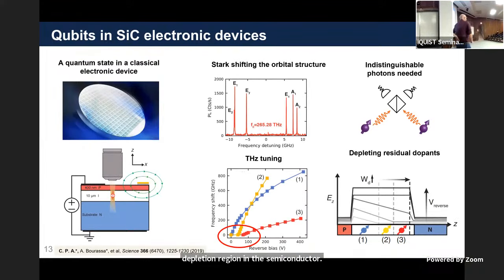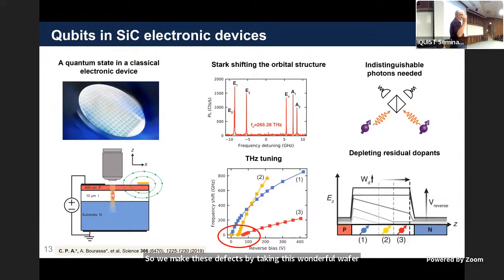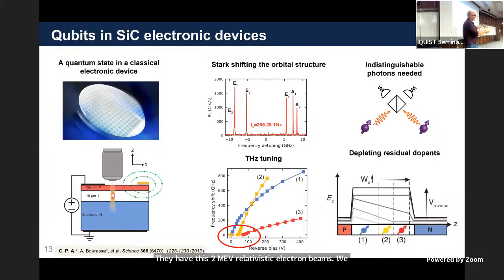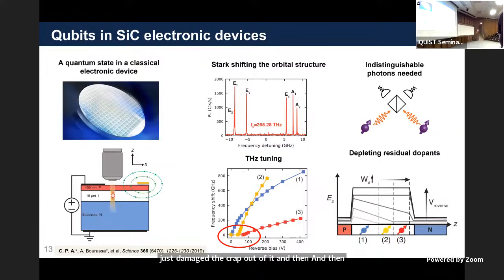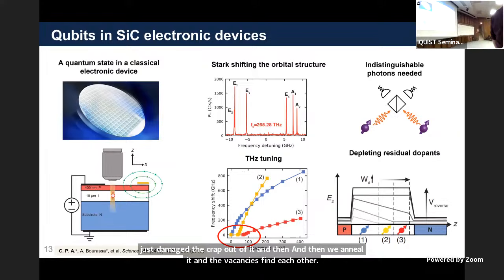So we make these defects by taking this wonderful wafer from this company. We ship it to Japan. They have this 2 MeV relativistic electron beam. We just damage the crap out of it. And then we anneal it and the vacancies find each other. So it's a sort of top-down qubit creation.